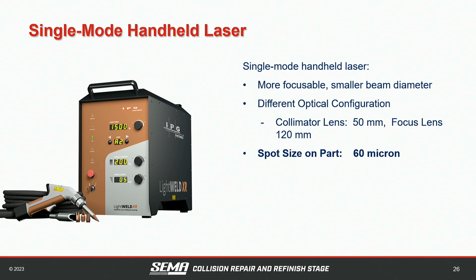Excellent. And also to touch on the thin aluminums as well, the single mode units handle welding with the thin aluminum a lot better because of the reflectivity of that material. It allows you to turn the power down and get more control when you're working with thinner materials, essentially. So how thin can we go? I've welded very thin in the 25 thousandths range, and with stainless and steel, I've gone into the 5 thousandths range. That's the same machine that'll do a 1/4-inch penetration into that same material. That's amazing.